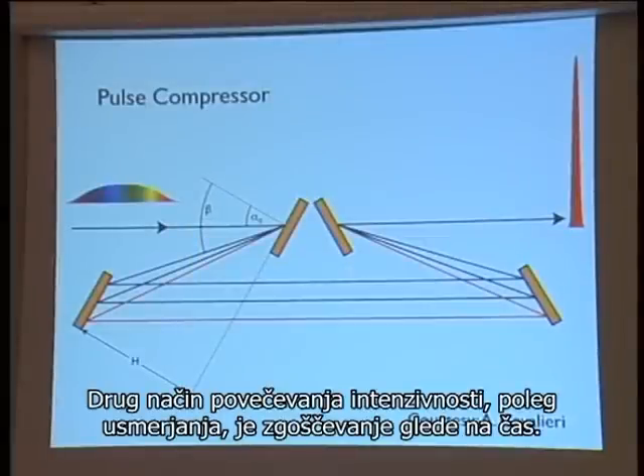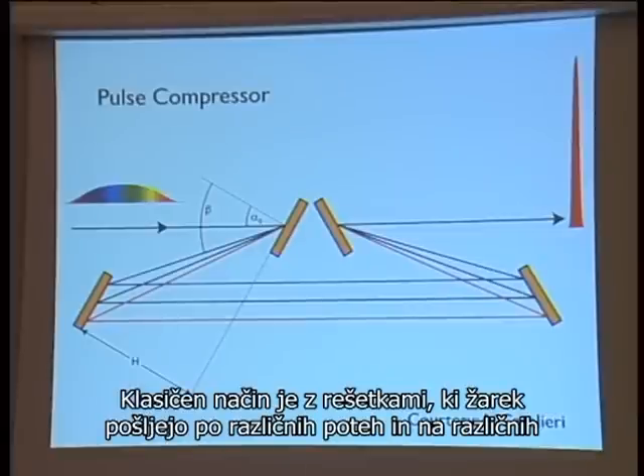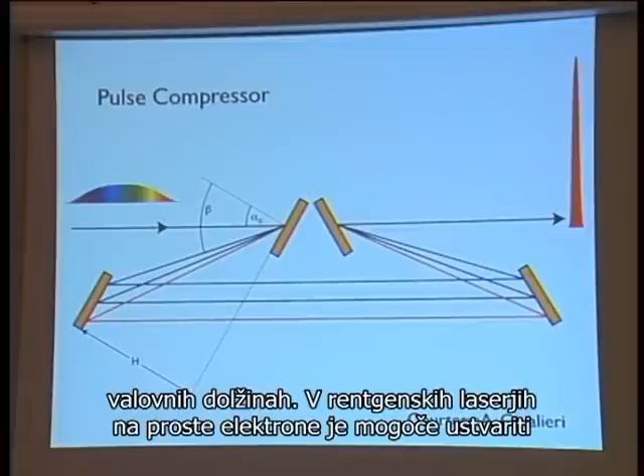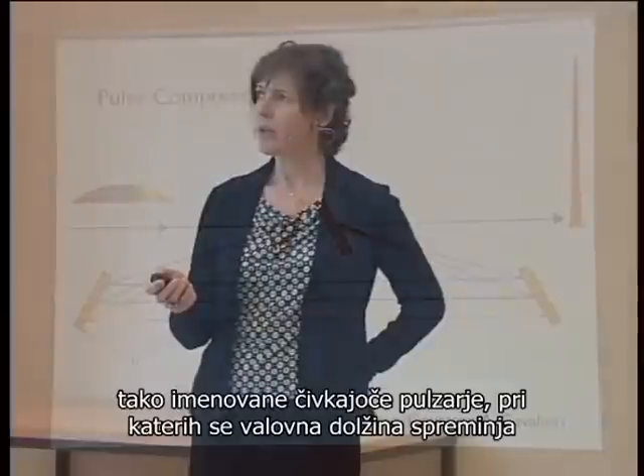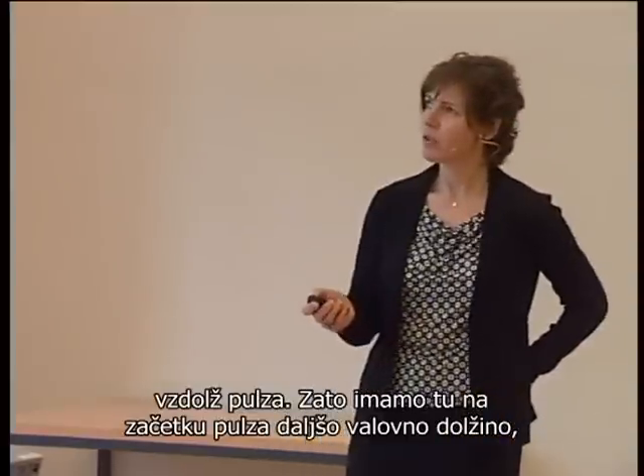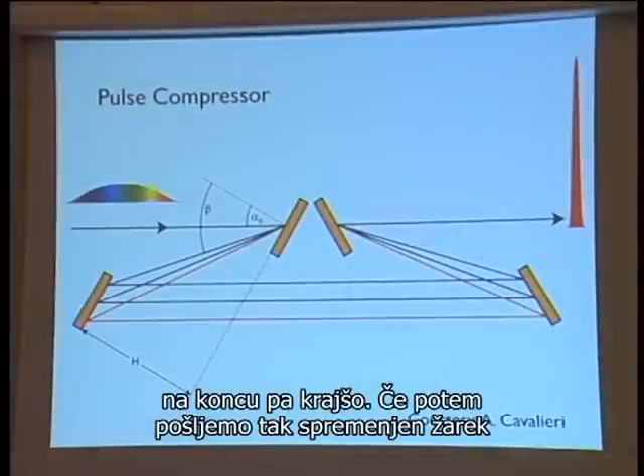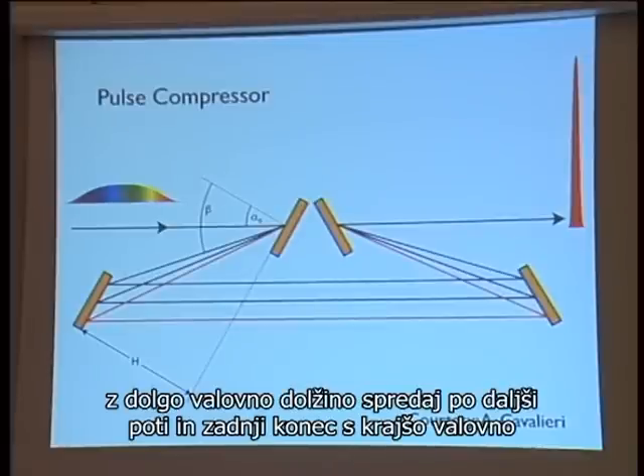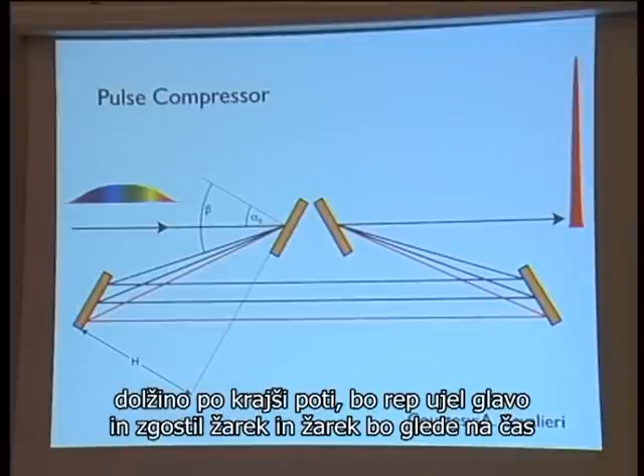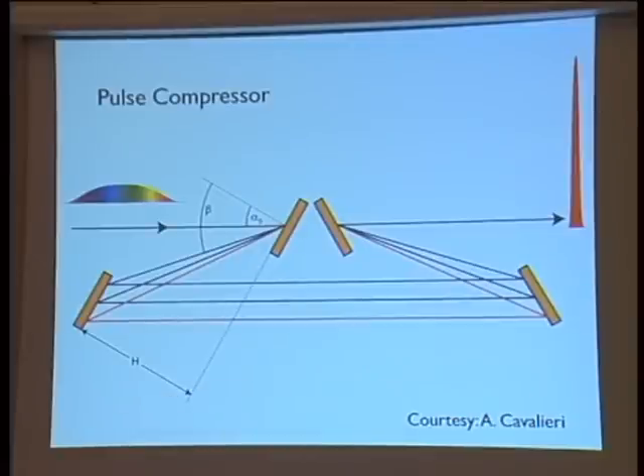Another way of increasing the intensity, in addition to focusing that I was just talking about, is to compress the pulse in time. Classically, this is done with gratings that send the beam along different paths for different wavelengths. In X-ray free electron lasers, it is possible to create so-called chirped pulses, where the wavelength varies along the pulse. Here we have longer wavelengths at the start of the pulse, and shorter wavelengths at the end. If we send such a chirped beam with longer wavelengths at the front along the longer path, and the shorter ones behind on the shorter path, then the tail will catch up with the head, and we will compress the beam. It's compressed in time and more intense.